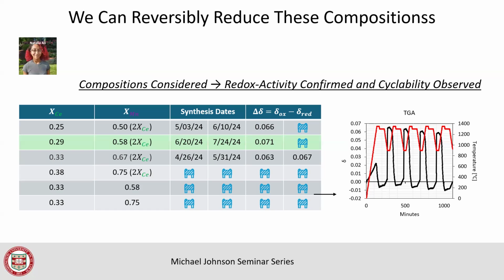So what do we care about here? What we want to see is that black peak go really high. The higher that black peak goes, the more oxygen we were able to drive off. But also what we want to see is that if we do this again and again and again, we see basically the same thing happening. That means that the material is undergoing a change. It's essentially reacquiring oxygen from water and becoming what it once was, basically back to its initial state. And then we do it again. And if it never decomposes, then we're in business. So this is really a promising sign.